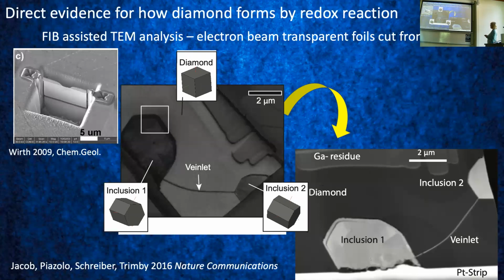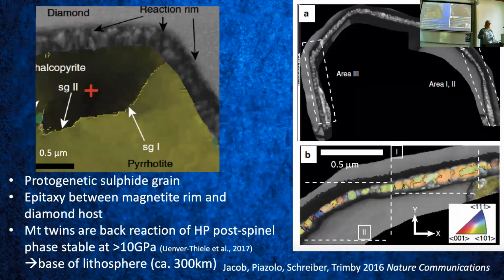That's another image of those two inclusions. And then you can perhaps just about see that this inclusion has a rim. So we got interested in this rim, and we used a method called TKD, which is transmission Kikuchi diffraction, just another method of electron backscatter diffraction, EBSD, on these FIB foils.